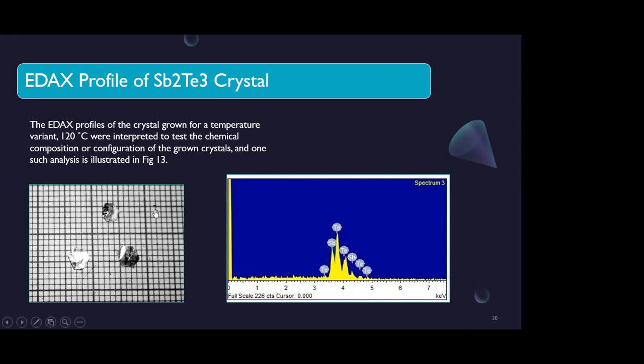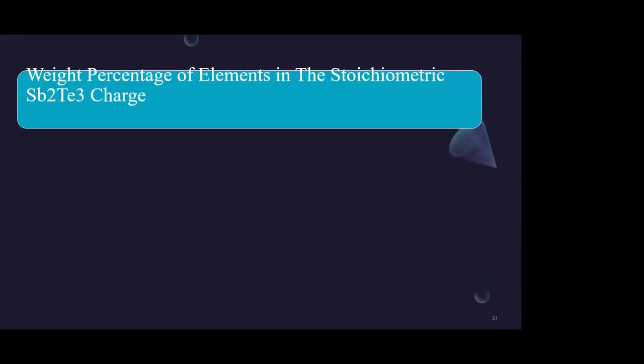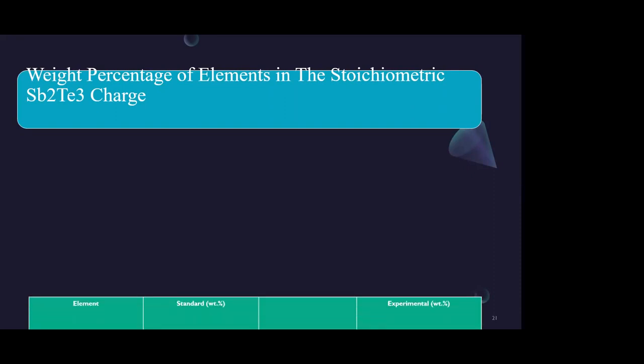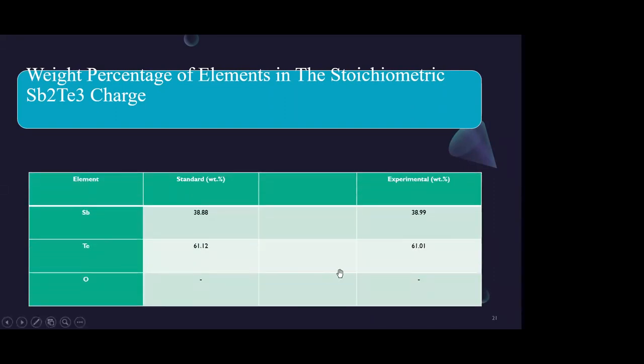And on the left-hand side, what you see is the crystal. On the right-hand side is the energy spectrum. And this energy spectrum clearly shows no oxygen content. So the weight percentage of elements in the stoichiometric Sb2Te3 charge, and you could see here very clearly no oxygen content, and it was well matched with the standard weight percentage. So the experimental weight percentage was almost coinciding with the standard weight percentage.